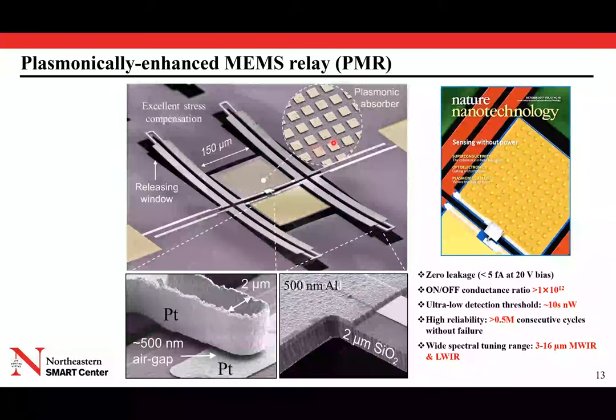Also, here you see these plasmonic structures that are part of that plasmonic absorber. We certainly put quite a bit of effort in making sure the overall fabrication process for this structure would give very smooth edges for those plasmonic structures, because it turns out that if you don't do that, because of scattering, it would be really hard to get very sharp absorption features that in some applications are very beneficial. Also here, I'm reporting some important performance metrics of these switches.